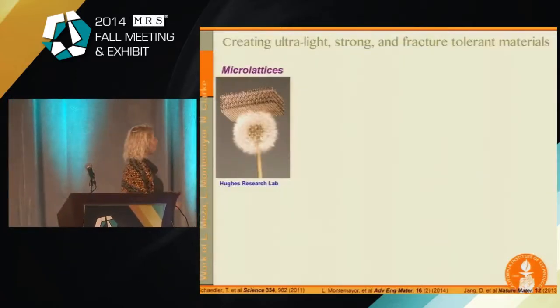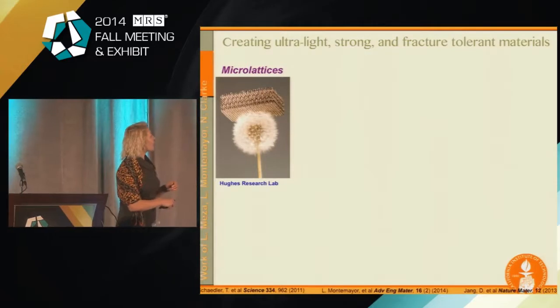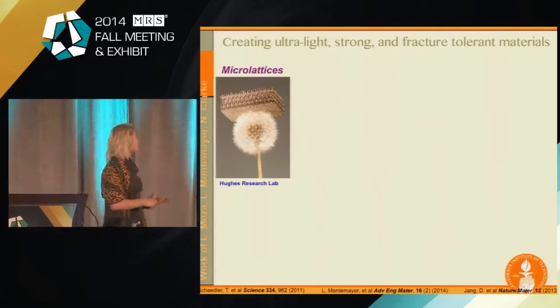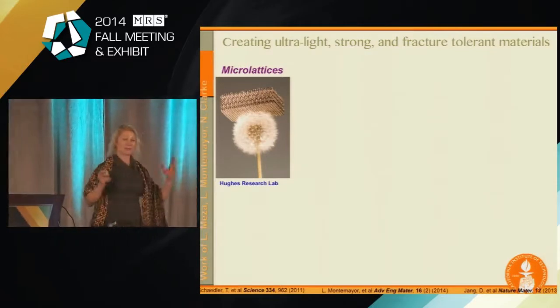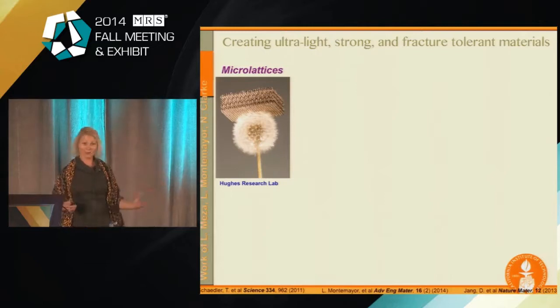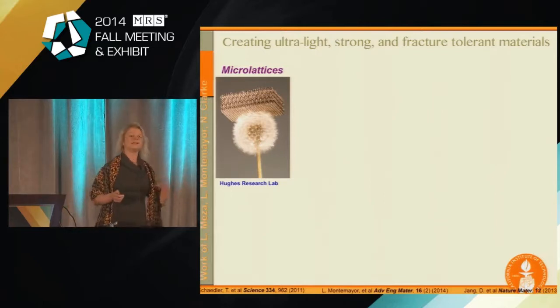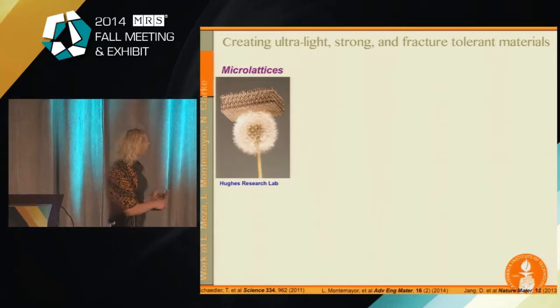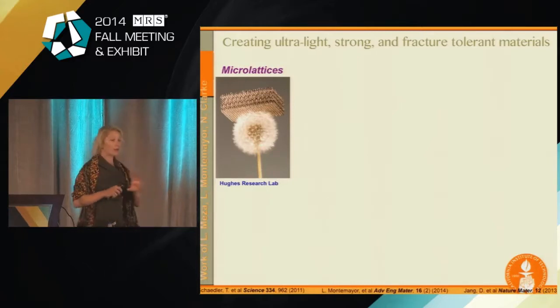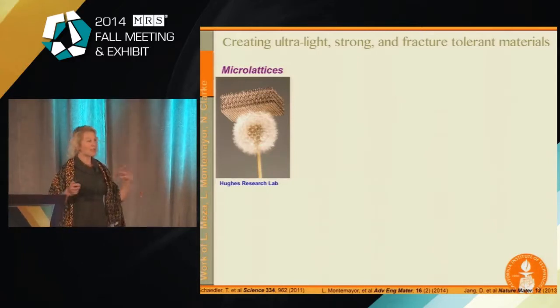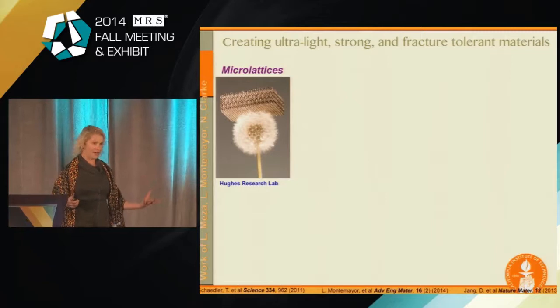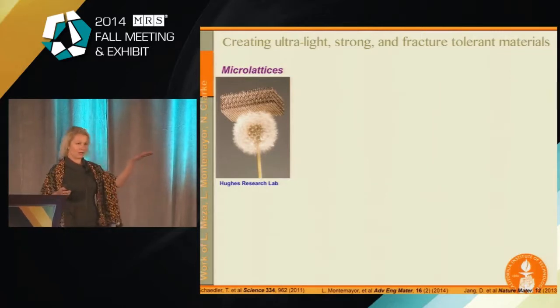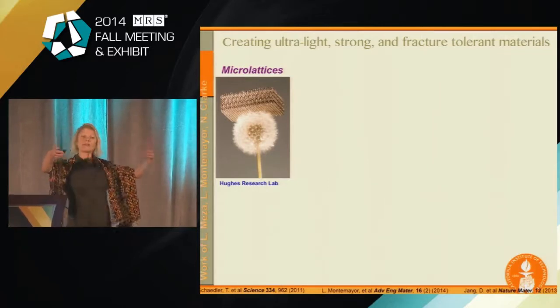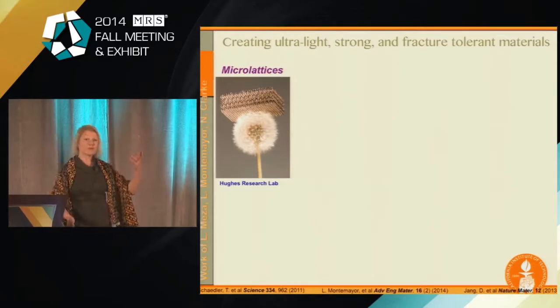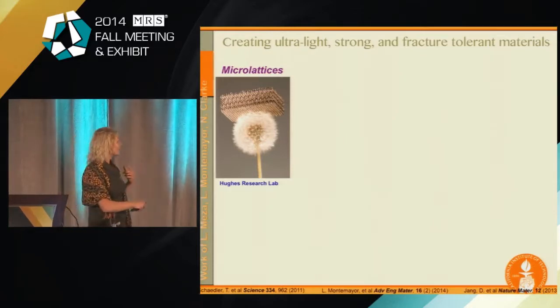So when we first started this work, we began with the microlattices, and some of you may have seen this image. This is a real microlattice that's sitting on a real dandelion. There's no photoshopping. This is not the world's strongest dandelion. This is a normal dandelion. And this microlattice that's sitting on top of it is made entirely of nickel, but it happens to be about 99.8% air. And so if I were to hold one of these microlattices in one hand and a feather in the other and release them in the air, the feather would fall down faster. These are really, really, really lightweight.